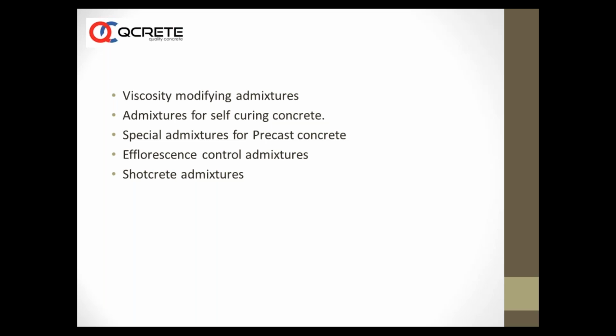It will not allow concrete to bleed, it will allow it to flow in a systematic way, and no segregation will be found. Such admixtures are used either separately, or now some companies blend them together with PC admixtures as an inbuilt two-in-one admixture - a PC based type G admixture blended with some amount of VMA. Normally, with any concrete mix, bleeding occurs up to 20-30 minutes, and after that it stops thanks to this kind of admixture. Earlier, we used to have admixtures where bleeding used to continue for 1 hour, 2 hours.